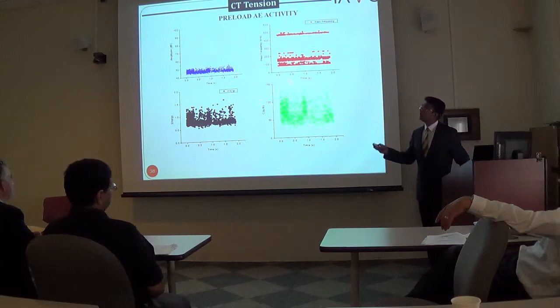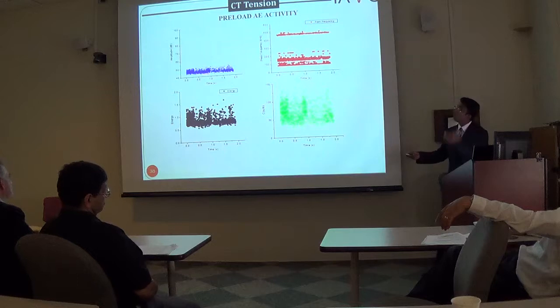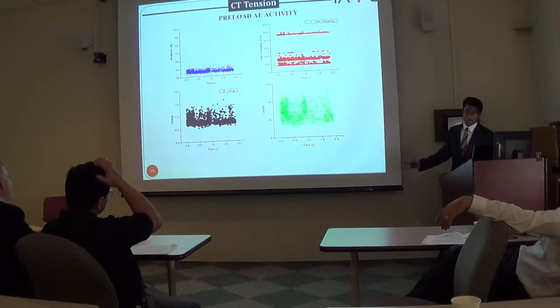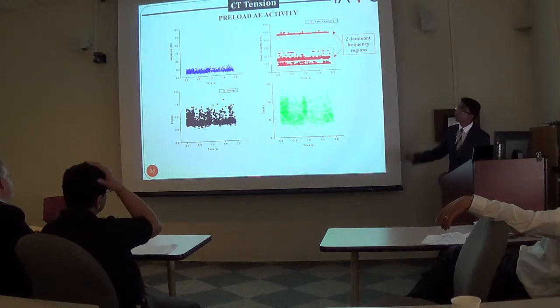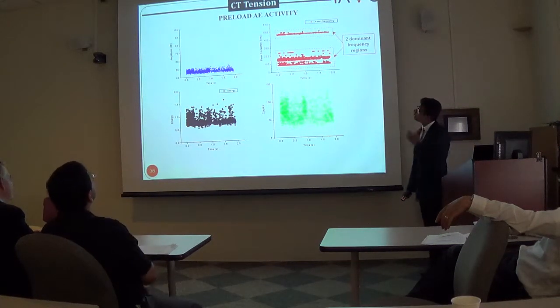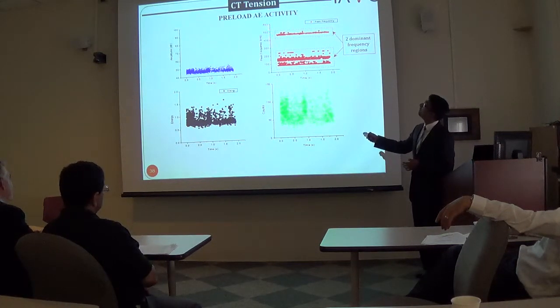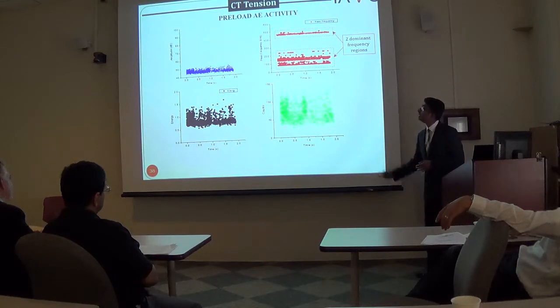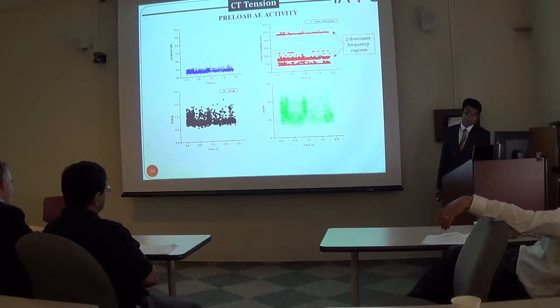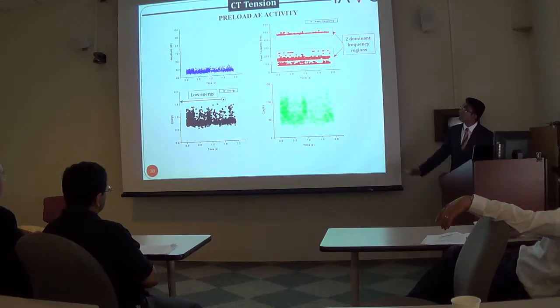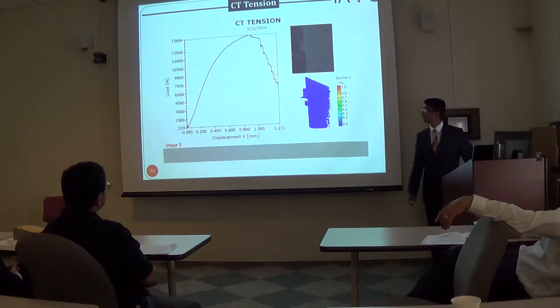However, the AE signals that were picked up during this preload were seen to be characterized by a very low amplitude, as seen here, and two dominant AE frequency regions were identified. Notably, frequency signals between 400 and 500 kilohertz and frequency signals between 100 and 200 kilohertz were noticed. Also, these signals were seen to be associated with very low energy and low counts.